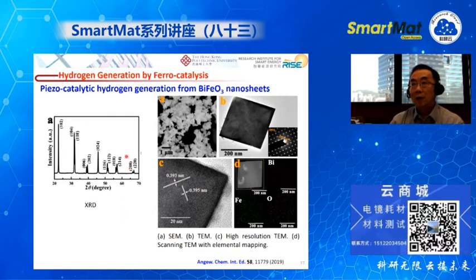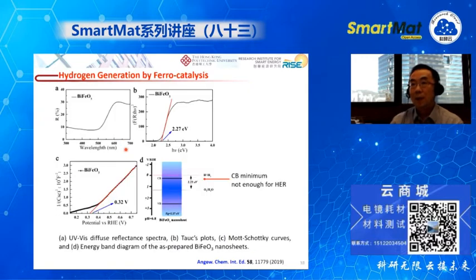And we also verify the piezocatalytic effect. We fabricate this bismuth ferrite nanosheet, and test its piezocatalytic hydrogen generation. A different situation for this bismuth ferrite is, if we characterize the band structure, we found the conduction band of this material is more positive than the hydrogen evolution. So this kind of material will not be able to generate hydrogen under normal situation, okay?